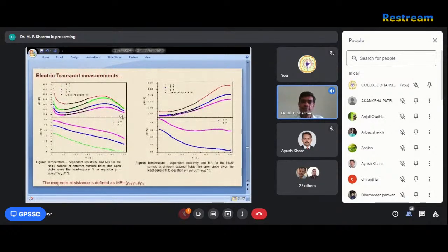So now we have fitted the electric transport measurement again, and then calculated the MR, magnetoresistance, which gives a different value. So at 9 Tesla it is a higher one. It gives 60% at the low temperature, and at the room temperature it gives almost 40%. When you increase the field, the MR is increasing. And we have to fit the